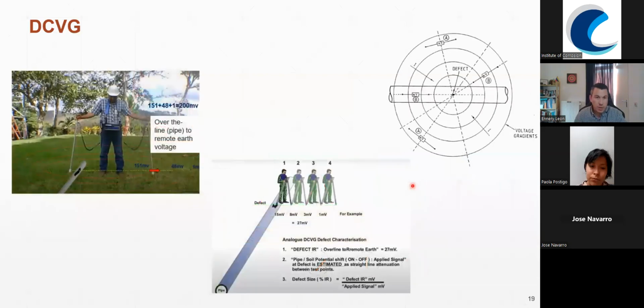Then the next step is, once you have identified a defect location, you need to move perpendicular to the pipeline to determine the remote earth potential. That is also known as the over-the-line pipe to remote earth voltage. So you will do several readings until you come to the point that you have 1 millivolt or 0 millivolt difference. For these readings, you are going to do each one approximately 1 meter apart, 1 meter, 1.5. Okay. Once you have a 1 millivolt reading, that's when you stop.